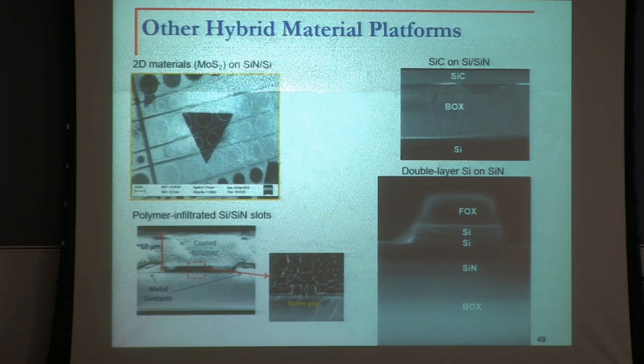This is 2D materials, molybdenum sulfide, molybdenum selenide. These are metal dichalcogenides, which combine a transition metal like molybdenum with a chalcogen like sulfur and selenium. And they have active properties. They are direct semiconductors, 1 atomic or molecular layer thin. And we are working on making quantum dots out of those. The paper just came out in ACS Nano, where we are showing lateral heterostructure in it.